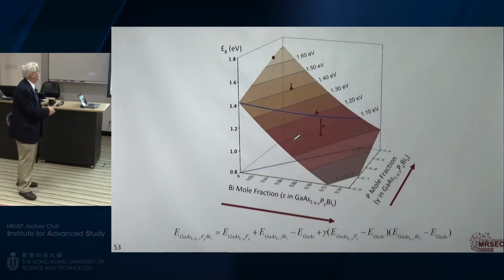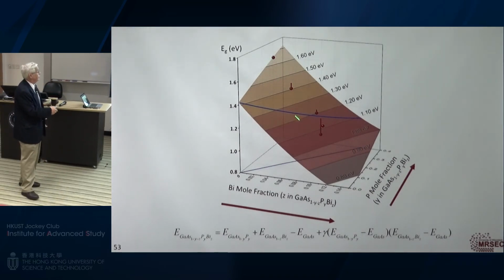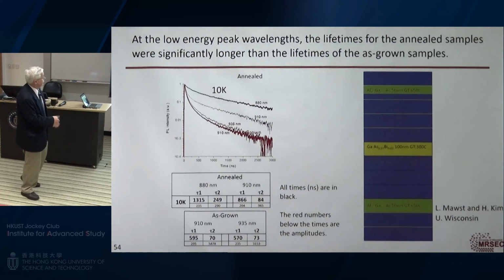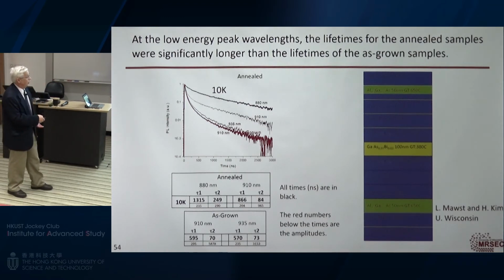And using the ideas that we developed on the gallium arsenide bismuth with the surface chemistry, we actually did grow this material. These lines here are where it's lattice matched to gallium arsenide, and we could change the band gap over a wide range because we had so many degrees of freedom with the extra two elements in there. We wanted to use this in a solar cell, for a 1 eV cell in a multi-junction cell, and even though it was metastable, once you formed it, it behaved perfectly well, as predicted. If I heated it up to a very, very high temperature, eventually it would fall apart.